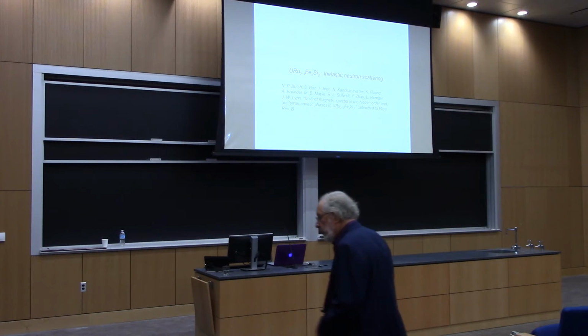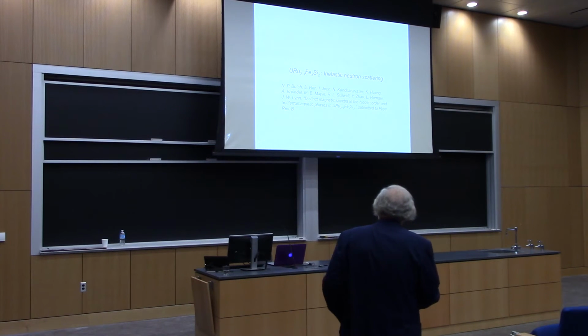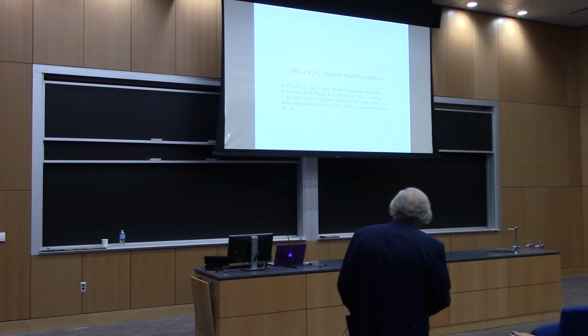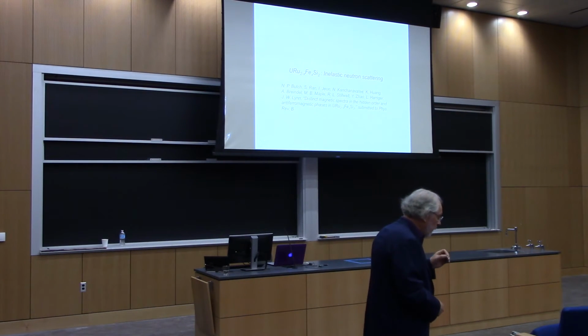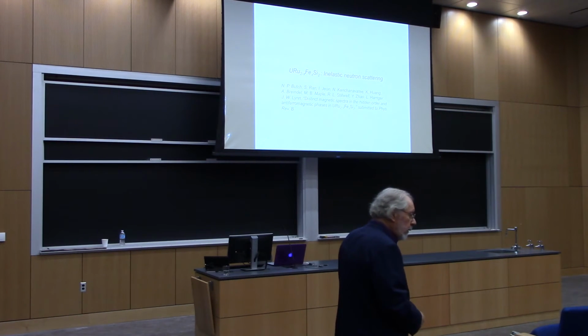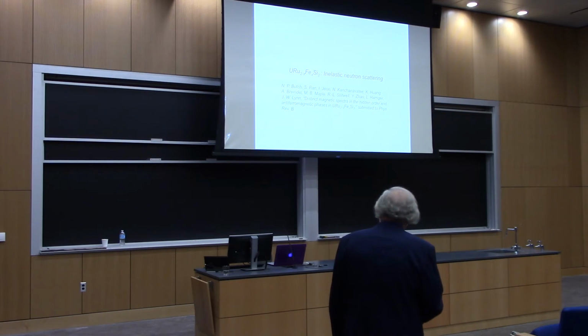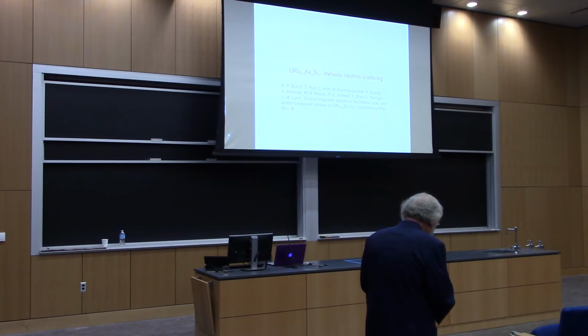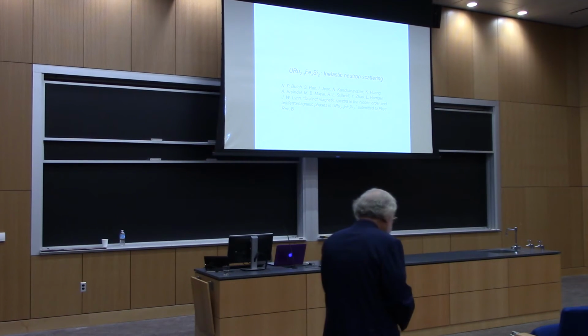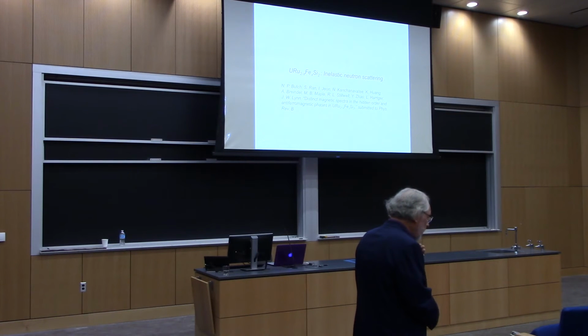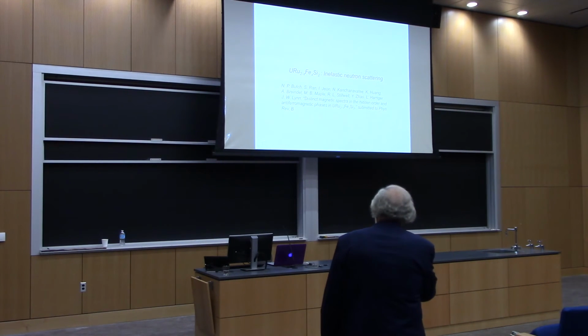Maybe I shouldn't, we're almost done. Let me just say that what I was going to talk about is some inelastic neutron scattering work. And so basically what's happening here is that the excitations for the commensurate and incommensurate phases that you see in the pure compound under pressure also occur in this system as you vary the iron concentration. So it appears then that this also maps onto the same type of behavior that you see when you apply pressure to pure URu2Si2. And then I was also going to mention some IR spectroscopy work by Tom Timusk and his group, where they actually measure the gap optically and see that it increases in magnitude as you go into the antiferromagnetic phase. And so it also appears to be consistent with this general picture that I tried to lay out.